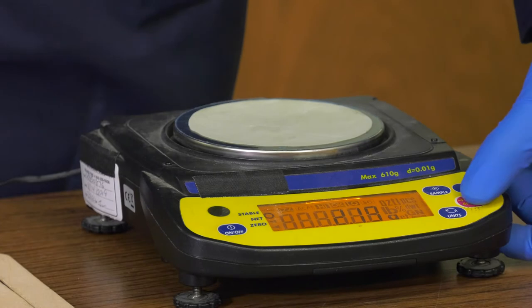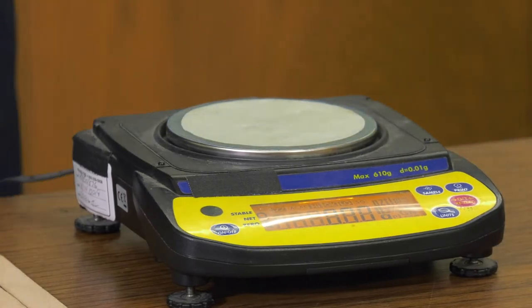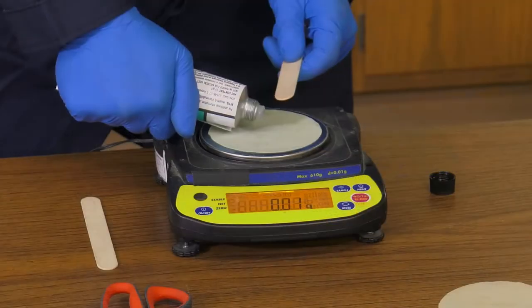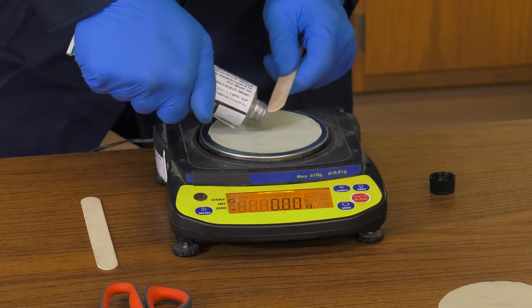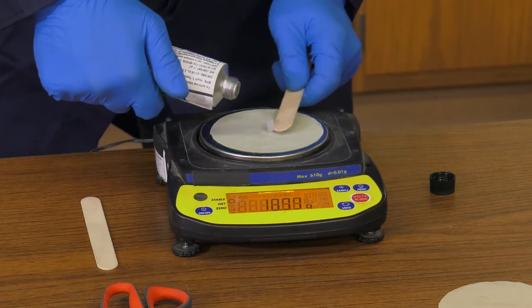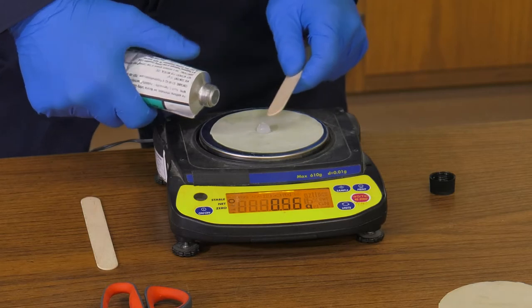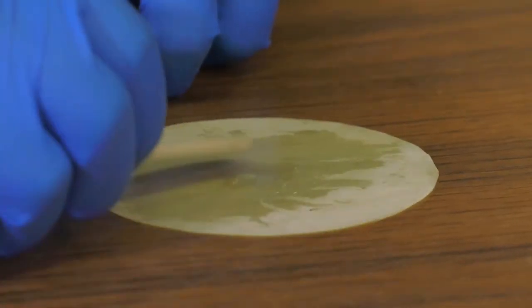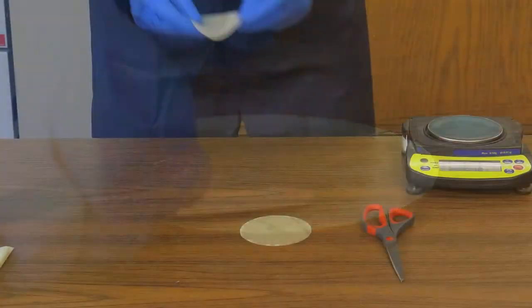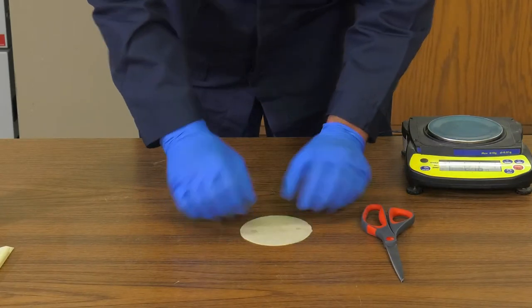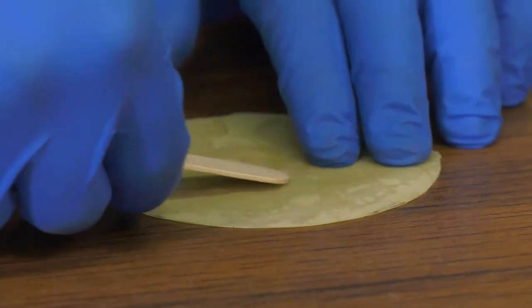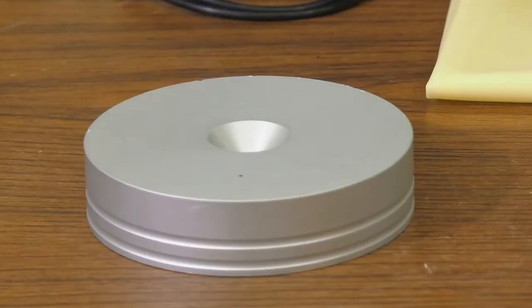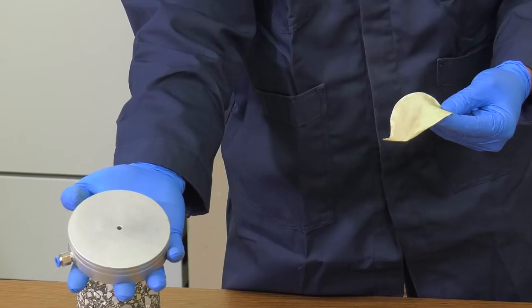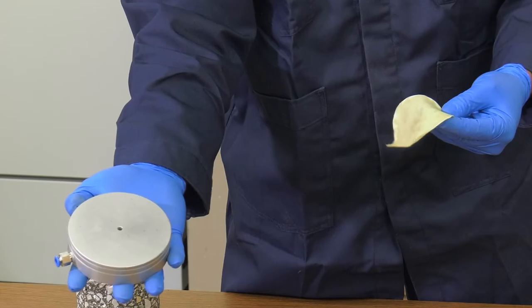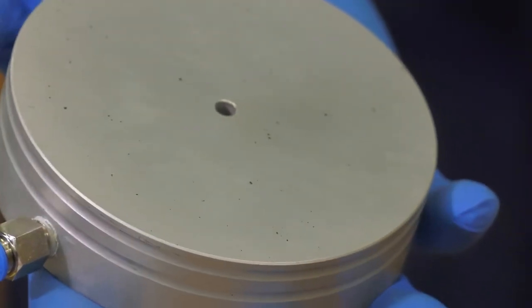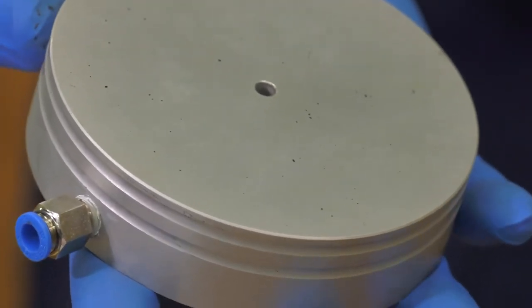First, prepare the end friction reducer using the circular latex membranes. Add approximately 0.25 plus or minus 0.05 grams of silicone grease to one of the latex membranes. Evenly spread the grease around the membrane. Place another circular membrane disc on top and smooth out with a wooden strip. This will be used with the upper platen. For the lower platen, you'll need a hole in the middle of the double-layered membrane that aligns with the vent on the platen for the drainage.